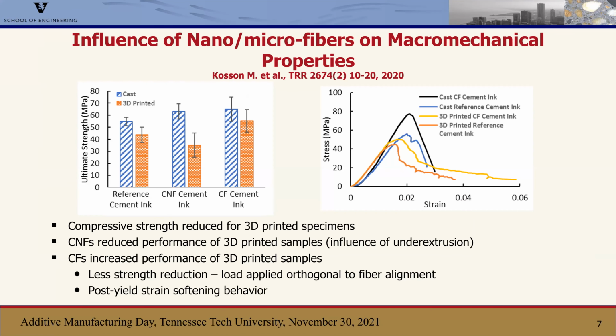So as for the effect of this reinforcement strategy on the mechanical properties, what we saw was that for all three of our inks that we're talking about here, the neat reference ink, the ink with the carbon nanofibers, and the ink with the carbon microfibers, there's a reduction in compressive strength between the 3D printed compared to the cast. We found that this reduction was the biggest for the carbon nanofibers, which we think has more to do with that under extrusion process and having less of a well-formed structure as compared to the actual reinforcement provided by the carbon nanofibers.